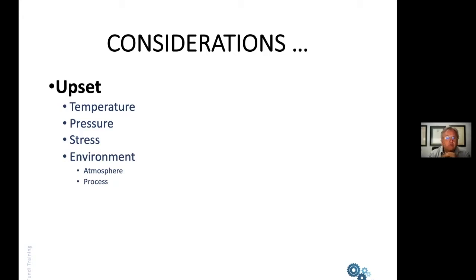These upsets can be in temperature, they can be in pressure, they can be in stress, they can be in the environment. If you select a material for a particular environment and then expose it to something else, don't be surprised if it doesn't work very well. And those environments can either be atmospheric environments or process environments. There was an incident where a coating system was selected for an indoor temperature-controlled, humidity-controlled environment, but during construction, the structure was exposed to sea air, the wind blowing directly off the sea, the structure being located very, very close to the sea. And the net result was, before the structure was even completed, the coating had failed because it was not designed for that particular environment.